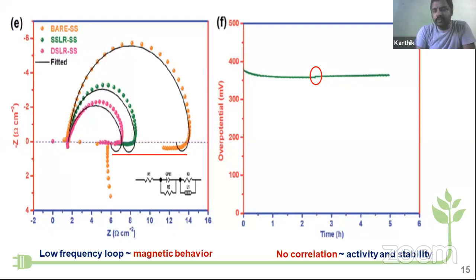And figure F is for the long-term stability test, that is, chronopotentiometric curves, recorded at a constant current of about 10 milliampere, because that is the fuel cell output current. Here, initially the overpotential is decreasing up to 2.5 hours. After that, it starts to increase and attains a steady state. This zigzag motion is happening because of polarization. That is, the surface oxides undergo polarization up to 2.5 hours. After that, the polarization stops, so it reaches the steady state. From this, we concluded that there is no correlation between the activity and stability of the electrocatalyst.